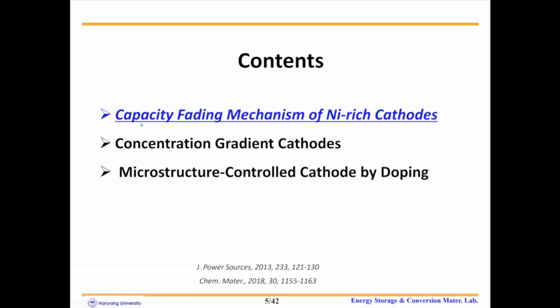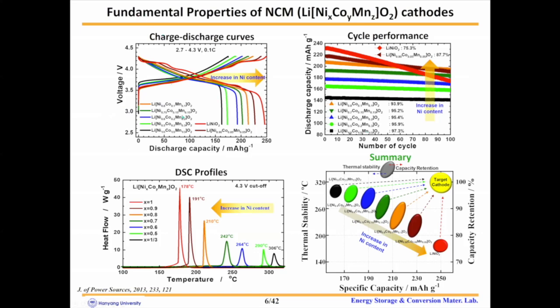I would like to introduce the capacity fading mechanism of nickel-rich cathode first. And this is the charge-discharge curves. As you can see, with increasing nickel content, discharge capacity almost linearly increases. And surprisingly, the pure nickel-rich oxide material delivered a discharge capacity of around 250 milliampere-hours per gram.